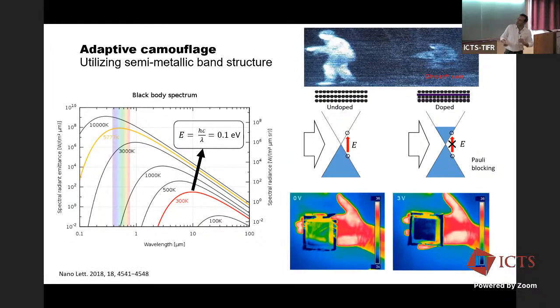And this can be demonstrated. You can see that this is a graphene-based system, and you can apply a little bit of electrical voltage to dope it, and you can see the hand has disappeared because the infrared radiation that has been emitted by the hand is not being absorbed or re-emitted. So this is one of the applications. I thought it's a fun application because it depends on the semi-metallic behavior of the graphene band structure.